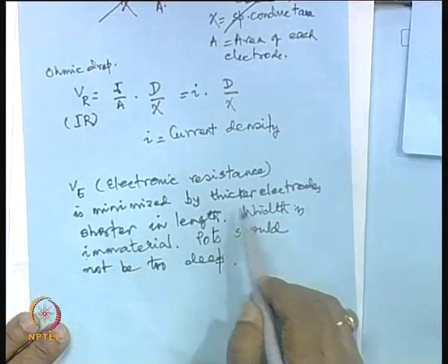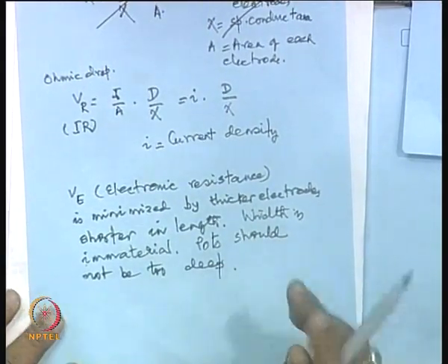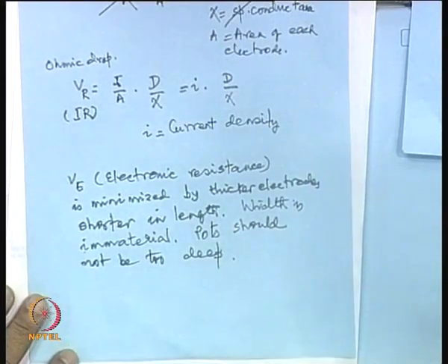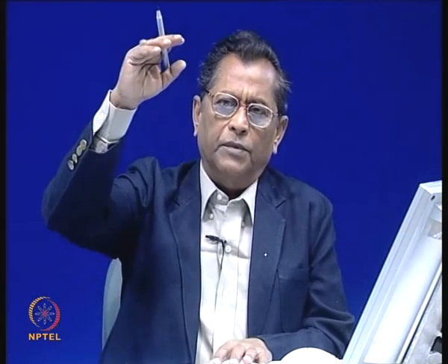We talk about the resistance due to electronic resistance in the circuit. That will be because of the circuit and also because of the resistances in the electrodes. Now, it can be shown by simple logic, the thicker electrodes will give you lesser resistance. If the electrodes are thin, the electronic resistance will be more, and also there is more resistance if they become too deep.